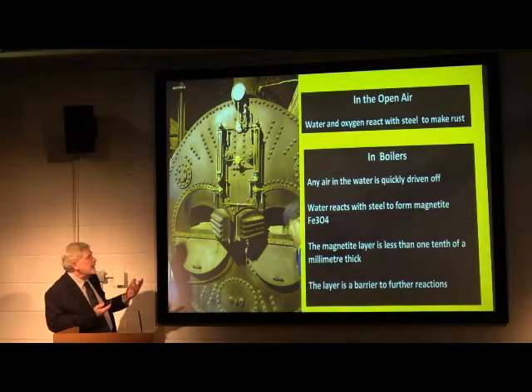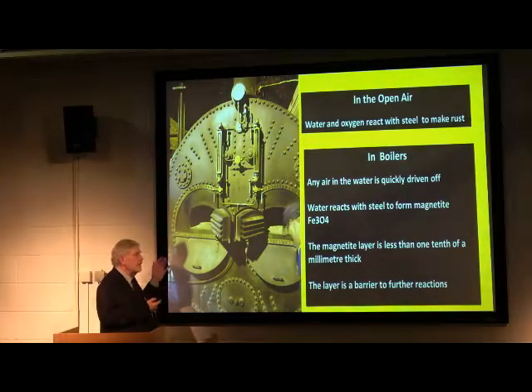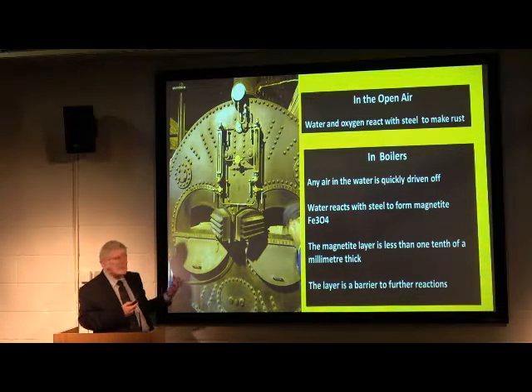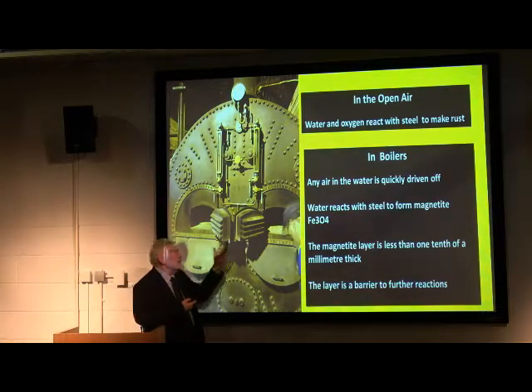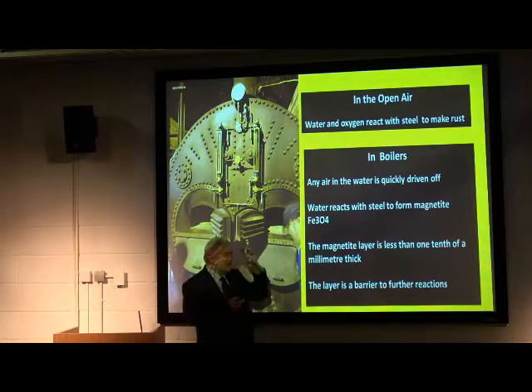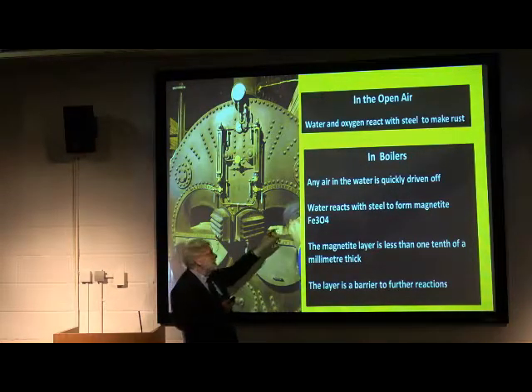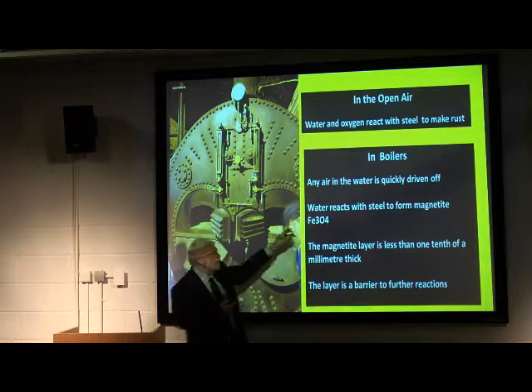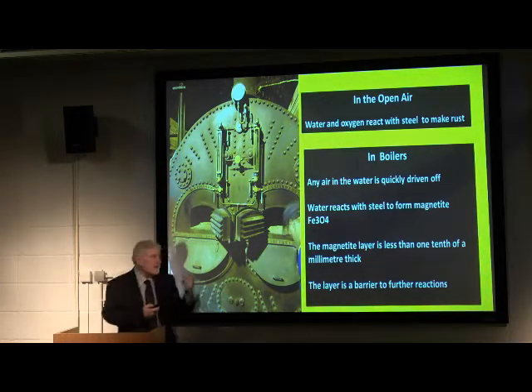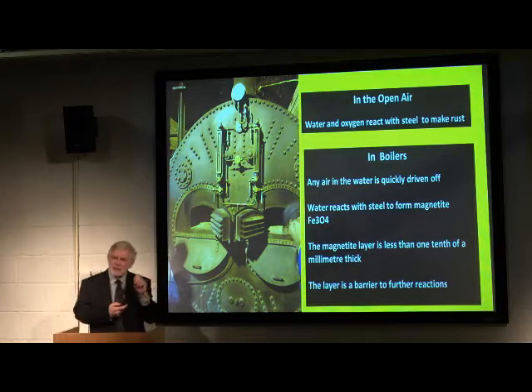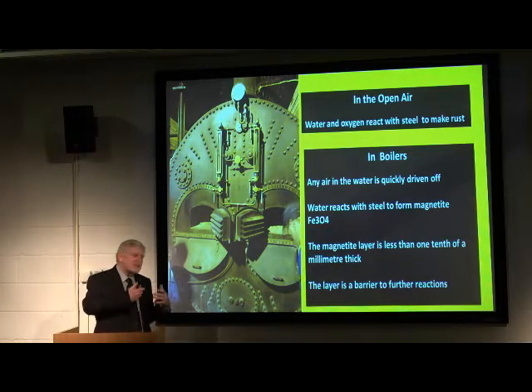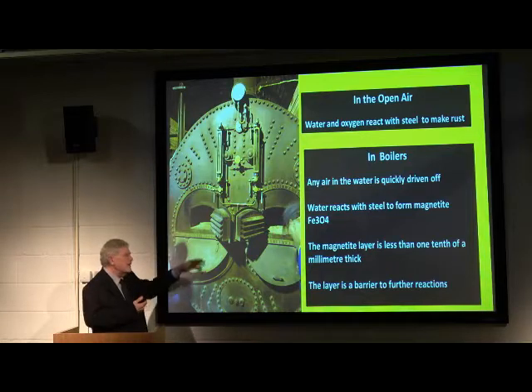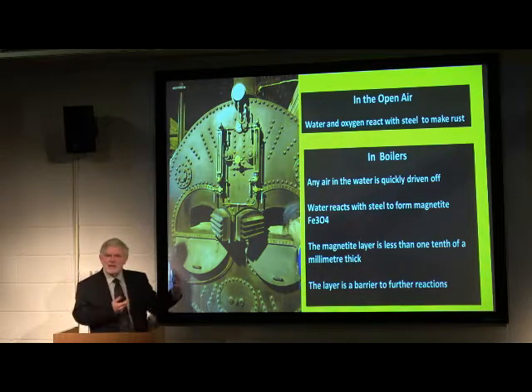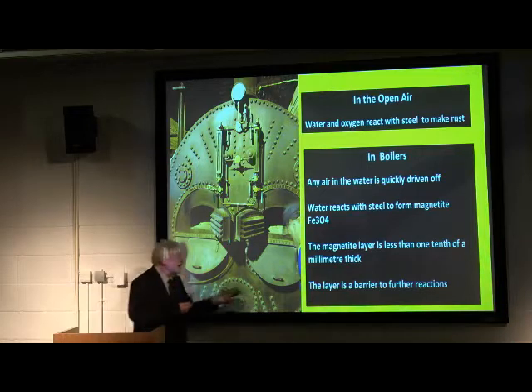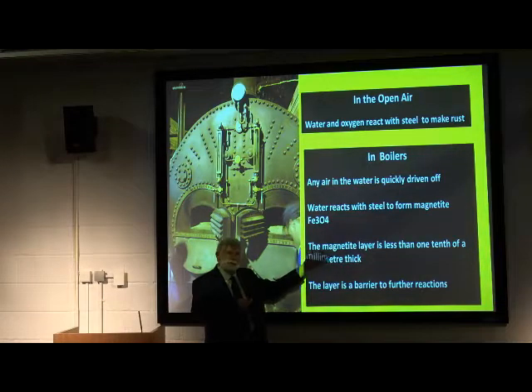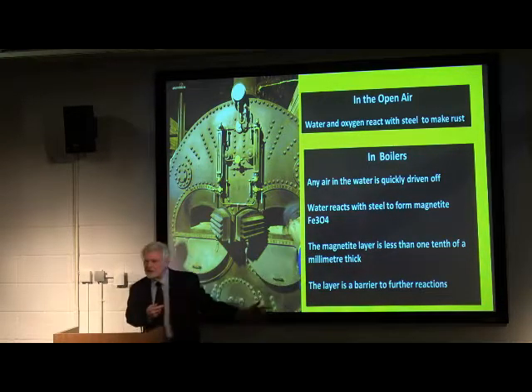And what is happening in the boilers is that the air that comes into the boilers is quickly driven off once the water boils. And then the iron reacts with the steam to form magnetite. And that magnetite is less than a tenth of a millimeter thick. And it adheres very, very well to the inside of the boiler, and it stops any further reactions. And if this didn't happen, we wouldn't have had an industrial revolution.